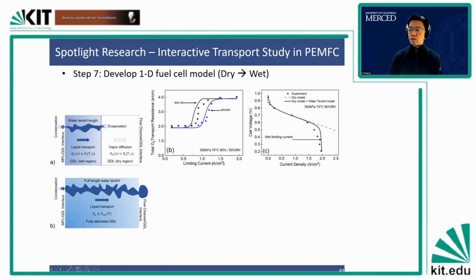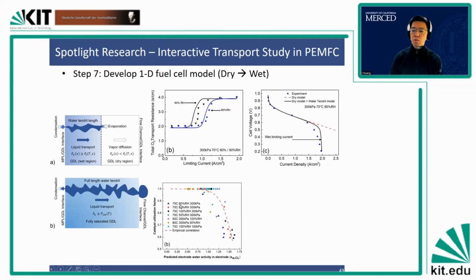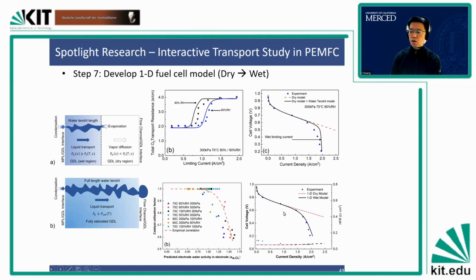And then we were able to go from the dry model, which is the red line, to the black line, which is the wet model. The symbols are experimental data. So you can see that we still fail to predict this transition here. But with that, we performed a lot of experiments to develop an empirical correlation for the electroflooding model. And after we implemented this two-phase electroflooding model, we were able to predict this performance well.